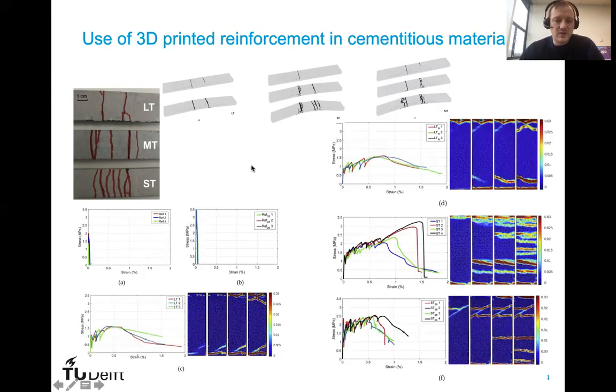And in uniaxial tension, we see that this is our reference material, which is of course very brittle. With large triangles, we can have a few cracks, but they're mostly obtained by pull-out of the reinforcement. And if we go to small triangles and small triangles with ribs, we can get multiple cracking and actually very nice strain hardening behavior, similar to what you get, for example, in ECC materials.